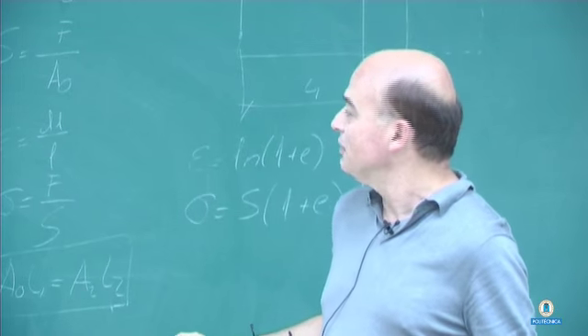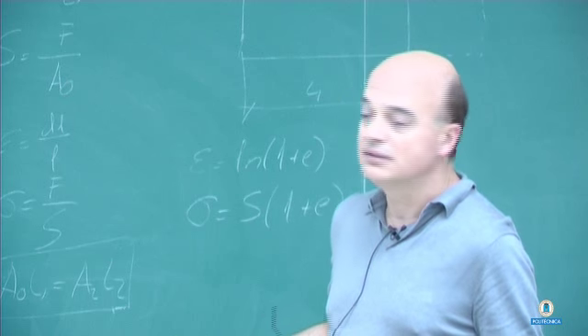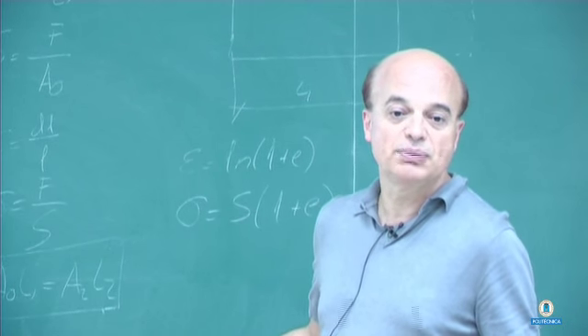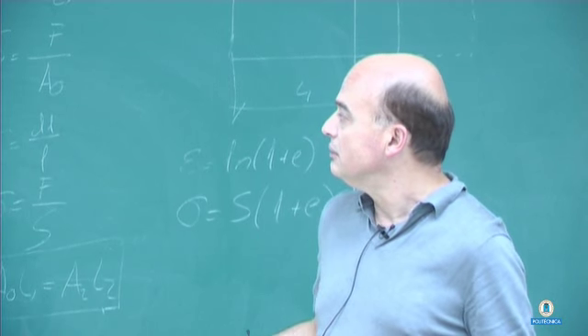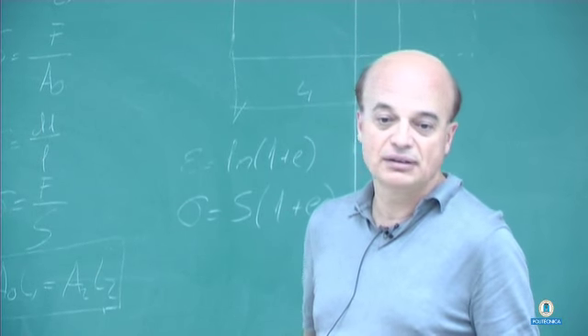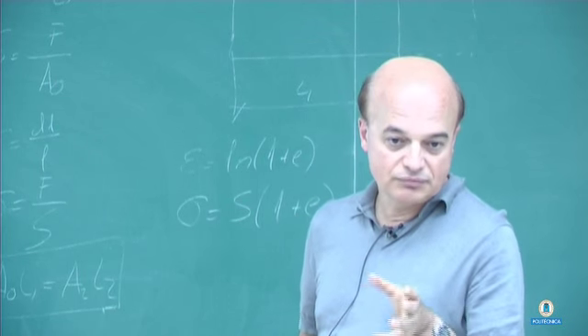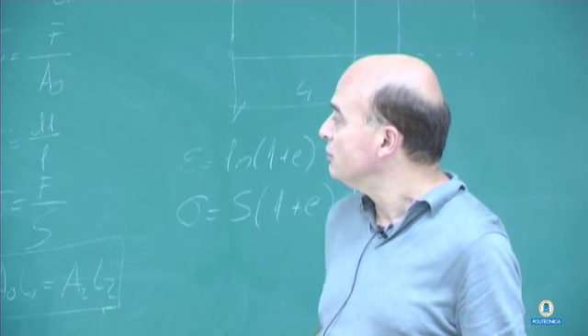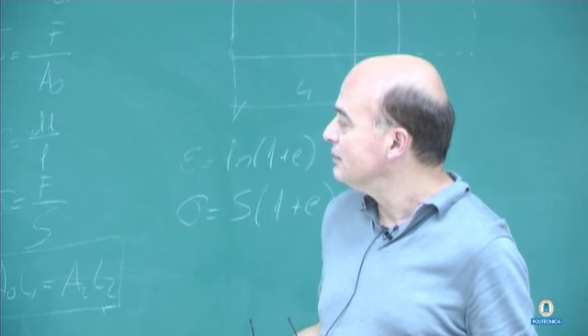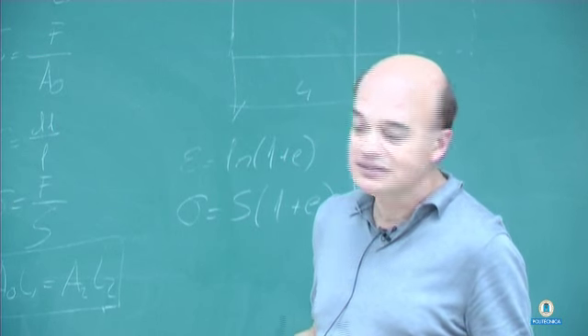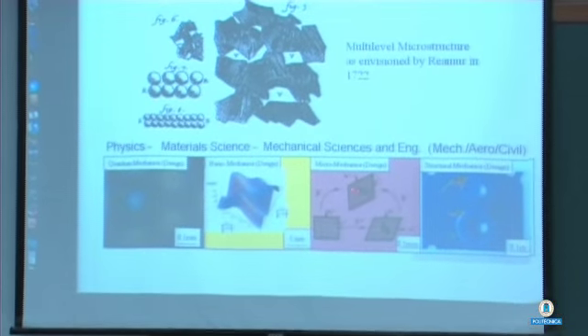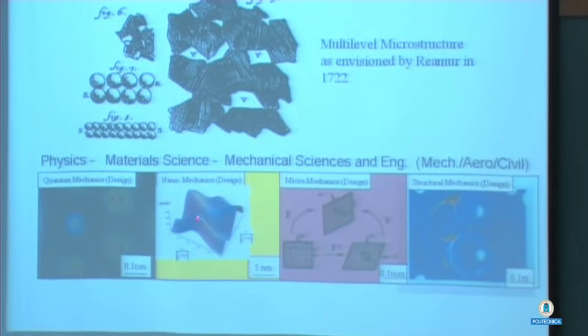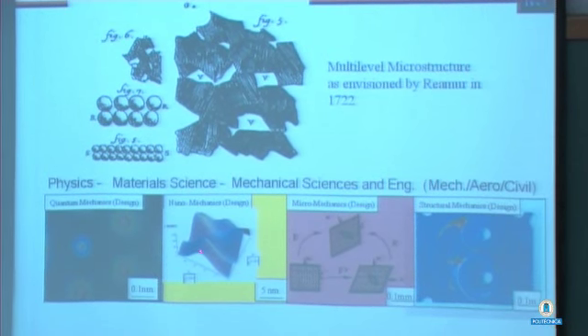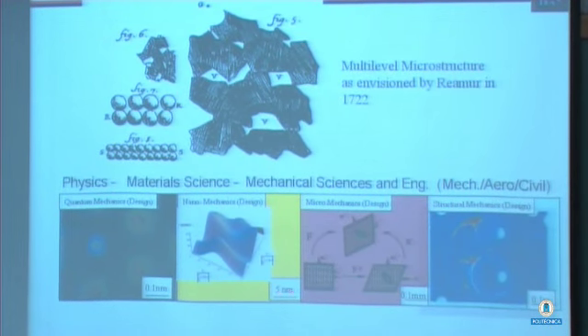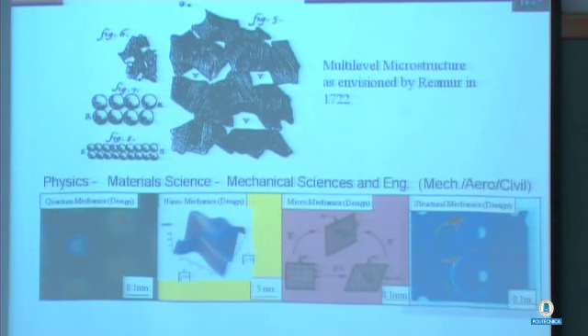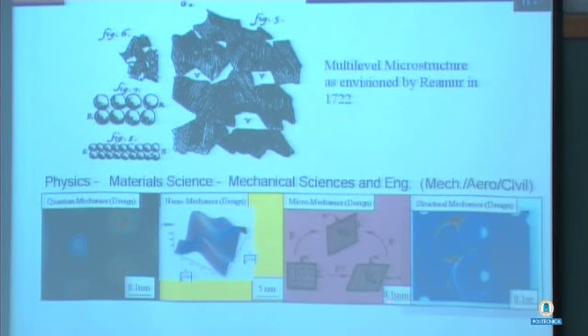In engineering, we work at macro scale, structural level, and that's the domain of mechanical, aerospace, and civil engineers. In the micromechanics area, we look at smaller length scales like inclusions or precipitates, and we describe the deformation with deformation gradient tensors, for example. And of course, what leads to these deformations are shearing of the atoms at the nanoscale. And that's of the order of 5 nanometers. This is of the order of 0.1 millimeters, or it could be 1 millimeter.